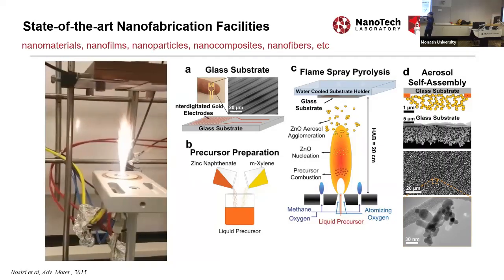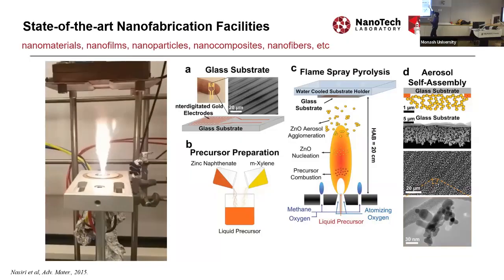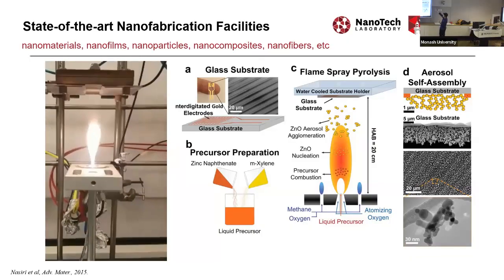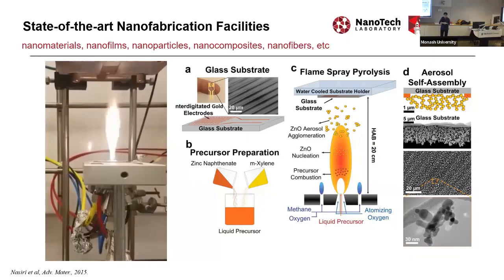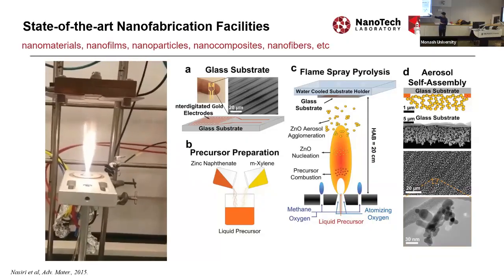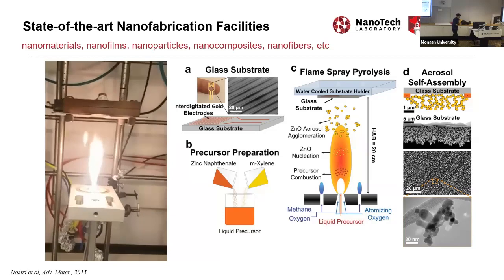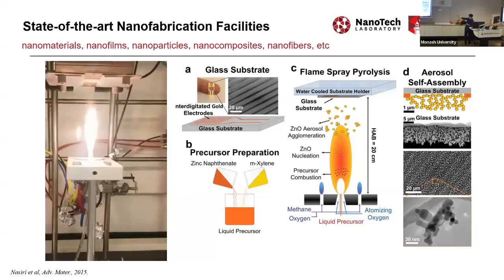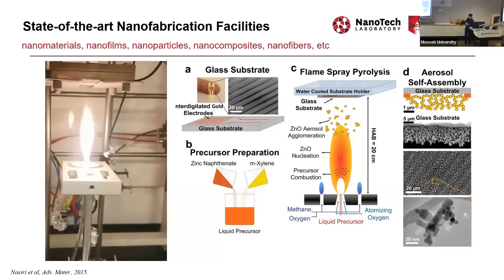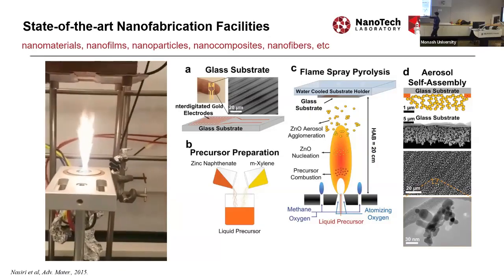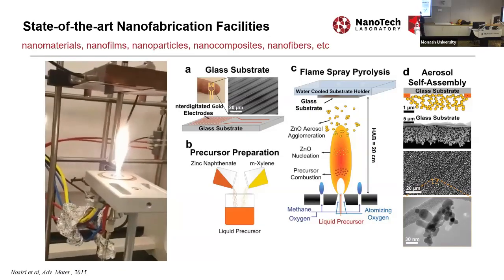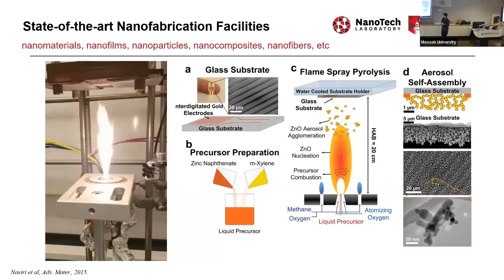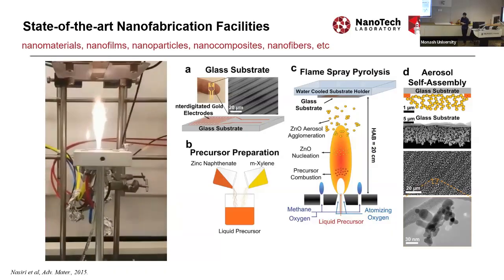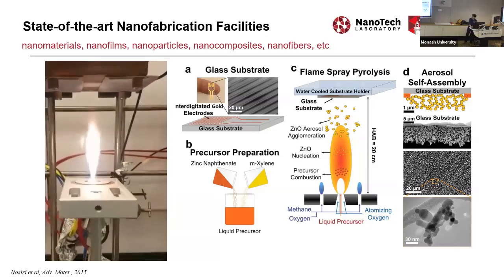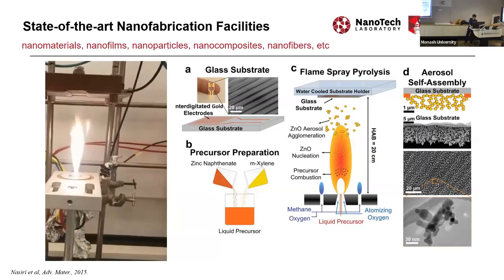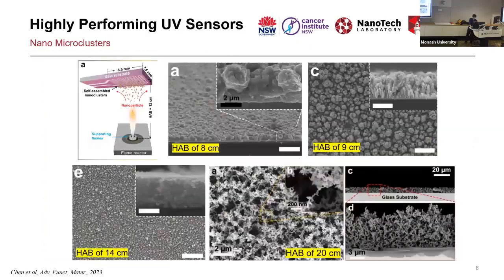So it is hot here, and very cold on the top, so the metal oxide nanoparticles work as aerosols. They go up and sit on the surface, and then they move based on Brownian motion, and that's why you end up with an extremely porous structure. And then you can do exactly the same thing with any type of metal atoms you want. You put tin, you end up with tin oxide. You put titanium, you end up with titanium dioxide. And if you put a noble metal here, you will end up with the noble metal because it's not going to be oxidized. So you can create gold nanoparticles or palladium or platinum nanoparticles by the same technique.